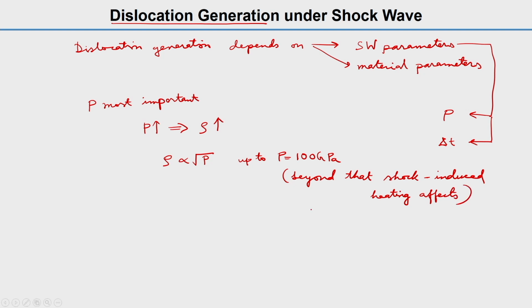Effect. So, that means after 100 gigapascal this dependence will be changed. But below 100 gigapascal pressure, it is very likely that the dislocation density is proportional to the square root of the pressure. For high stacking fault energy FCC material, we will discuss some materials, and mostly it is FCC materials, and specifically right now we want to tell you about the high stacking fault energy FCC metals or alloys, let us say FCC materials we write.